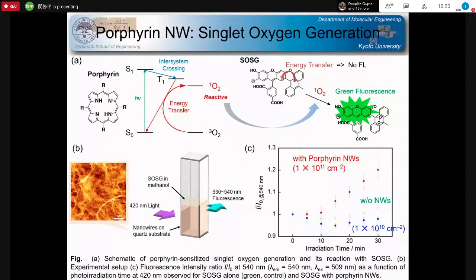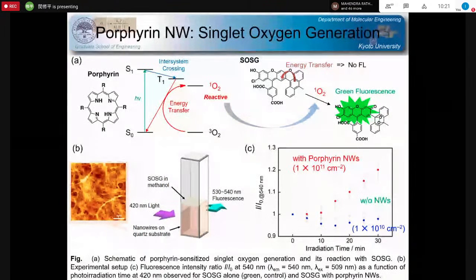In this case, this is the excitation of oxygen. As you know, the ground state of the oxygen molecule is a triplet state. But anyway, after the energy conversion from the porphyrin nanowires to the oxygen molecules, singlet excited oxygen molecules were generated. As demonstrated in this viewgraph, upon excitation with ultraviolet or visible light, highly efficient excited oxygen molecules were generated. So this result suggests that nanowires are also applicable for future medical treatment, to cure unwanted cancer cells or other kinds of biomedical reactions in our human bodies.